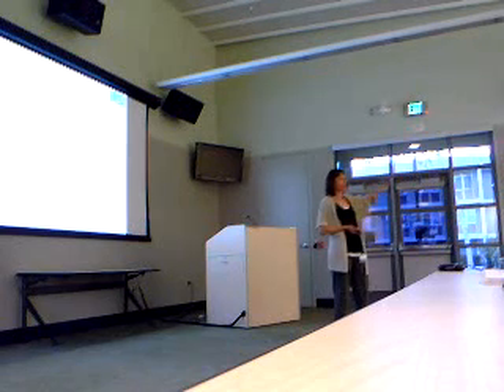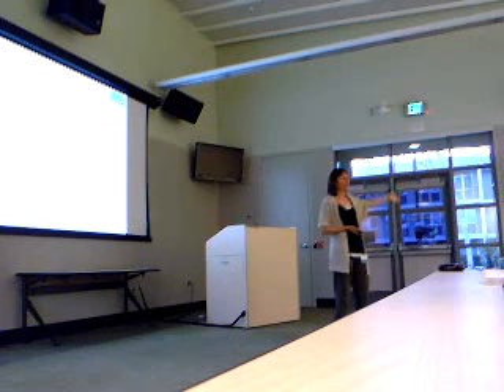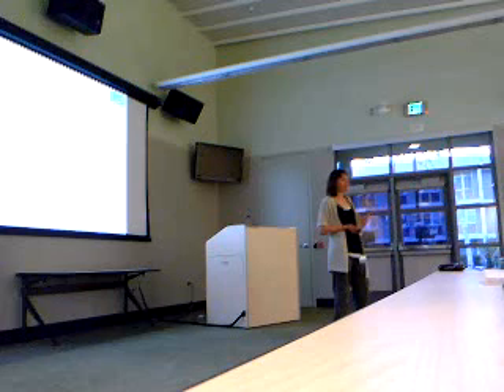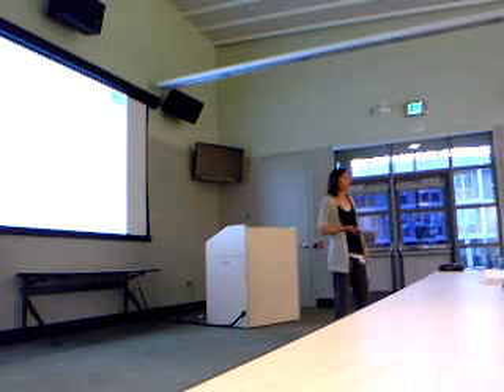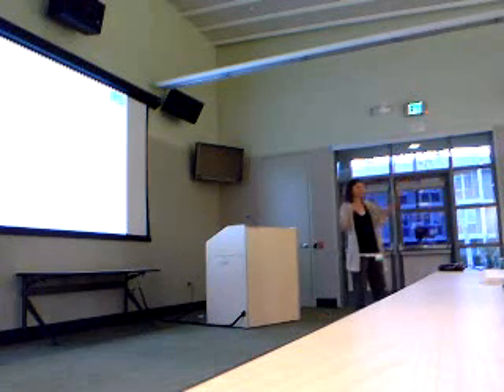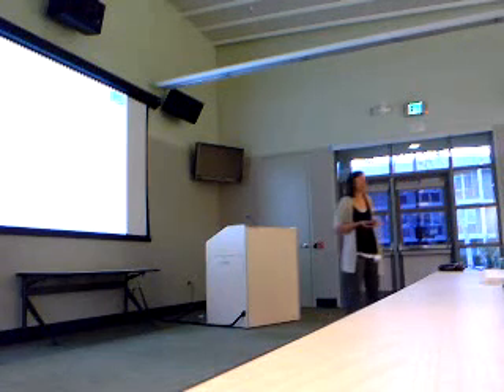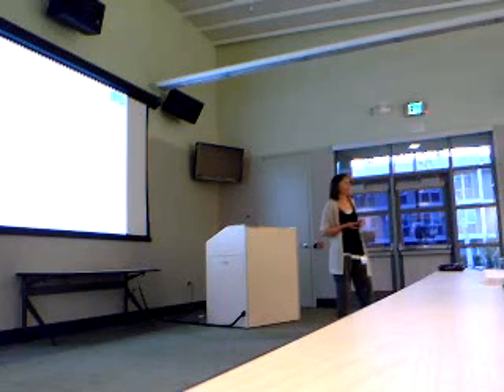vary it over a range of physically likely values. And if the qualitative physics doesn't change over that range, then we go and have a beer and say we're good. But the calculation could be very time consuming, right, if you choose all the U? Well, that's not terrible. We go from U equals 0, where it's the LDA, through 10 electron volts. That's the range you need to span for any realistic material. And for many materials, there's no qualitative change over that range.